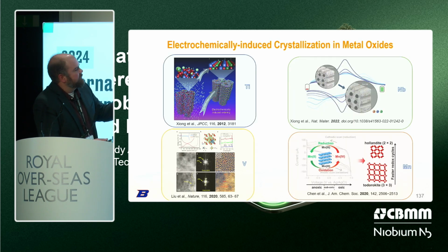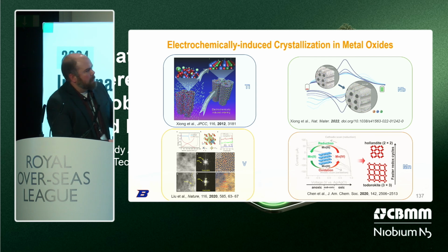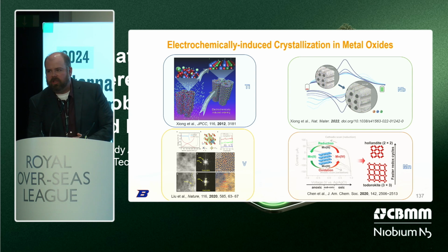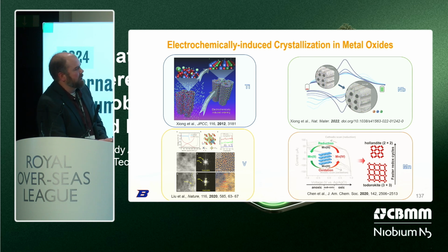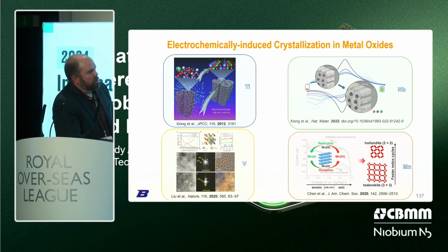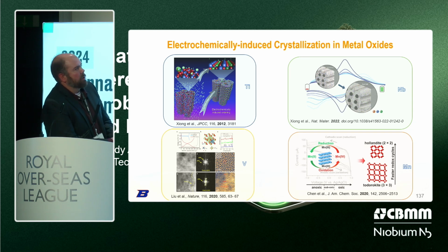And to kind of summarize, we need to think more than just adding heat to a material to create structures that we want. We want to think about electrochemistry as something that can get us to these metastable states that have better properties for batteries. And so, for example, Claire's work showed in the TiO2 nanotubes where they had the amorphous to cubic structures. And then we have all the work that I discussed here today showing that the niobium oxide can also go through that same phase transformation.